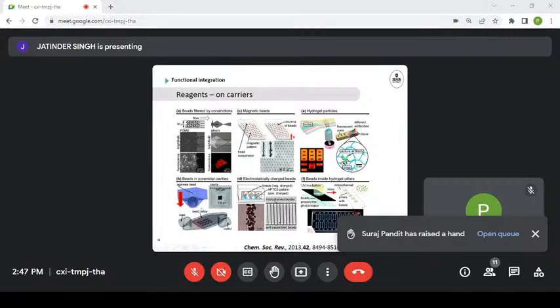This is a particularly nice one where they used beads in little cavities, and they applied a small negative pressure to keep all the beads in place. And this allowed them to do assays at a very small format, because they used the antibody functionalized beads to do an ELISA on, and they could very precisely define the location of all these beads, because the array that they'd created only had place for one bead in one spot. So you just flood the whole device with a bead suspension, you apply a little vacuum, each hole traps a little bead in place. You can then wash with a clean solution without beads, the beads that haven't been trapped away, and you can do a very accurate ELISA assay on the individual beads, because you know that every hole only contains one bead, but all those beads contain the antibodies supporting your ELISA assay.